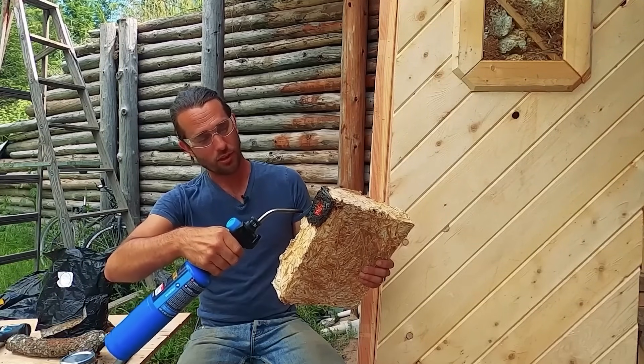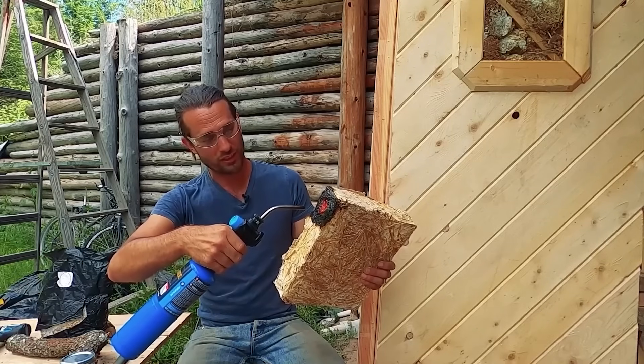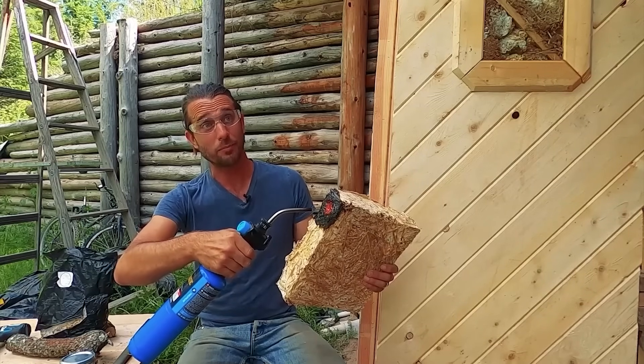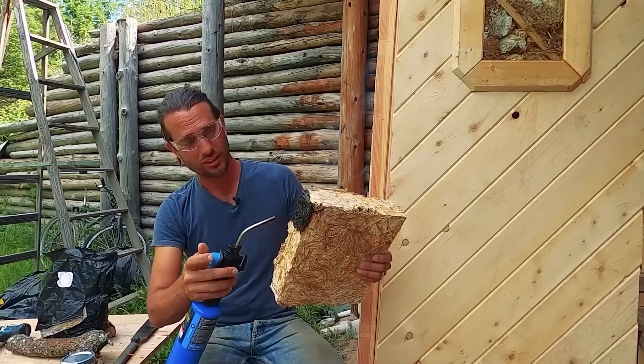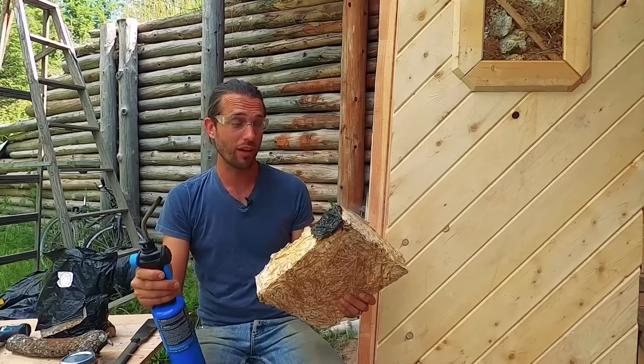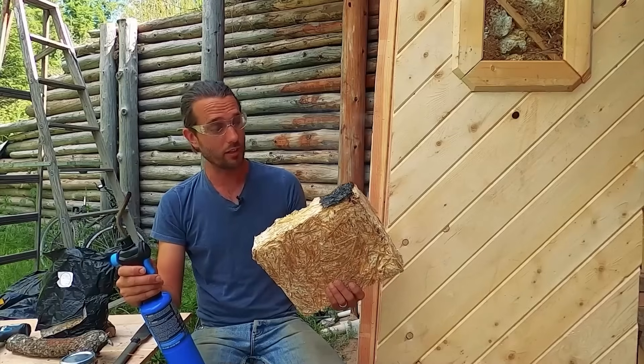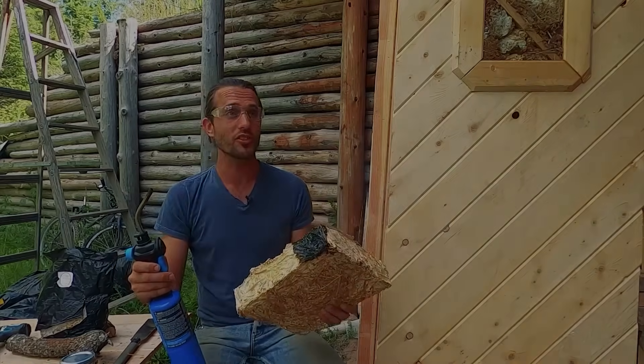When a mattress company makes a new mattress, they have to do testing called a direct flame test — you've got to be able to do this for 45 seconds or so — and usually what happens at about a minute is the entire mattress goes up in flames. The nature of those fire retardants that are usually used is they work really well until they quit working, and then they fail catastrophically. So the fact that this can burn for this long without catching fire is a really incredible property that we really like in buildings like homes.